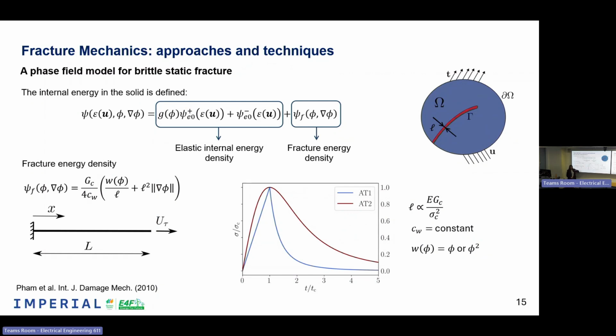With this, we can define the parameters. You can see that L, the phase field length scale, the so-called phase field length scale, is also a property of the material. It depends on GC, on sigma C. CW is a constant. And finally, the function W phi, it can be different if we consider that, first of all, in the first part of this graphic, there is an elastic threshold, so no damage. This would be phi. Or phi squared if we consider that from the beginning the damage is growing, although it's not important enough to propagate or to generate the crack.